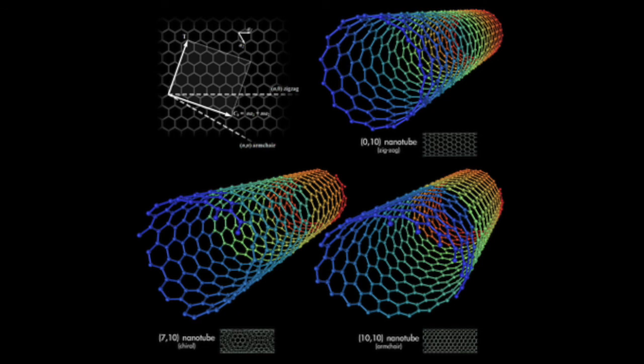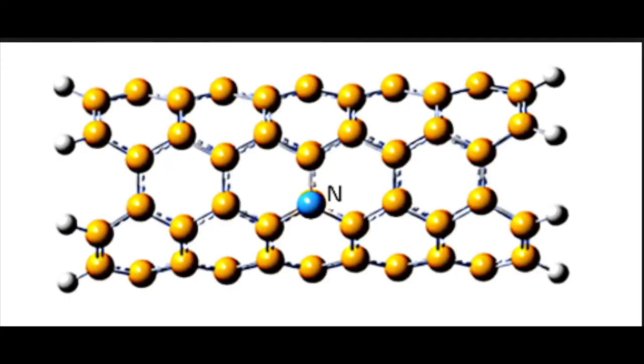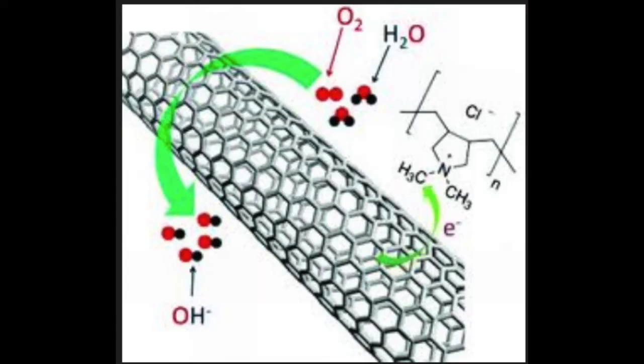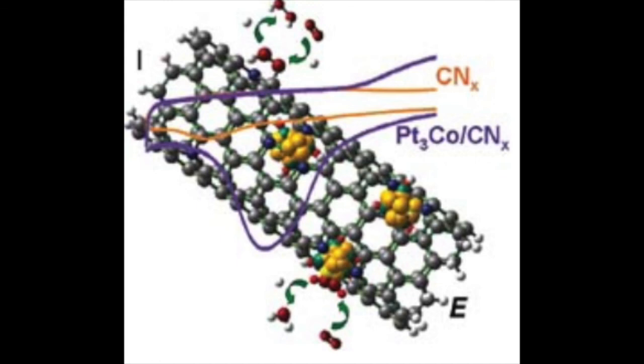There are also a few ways to dope carbon nanotubes, to make them n or p-type. First, you could add impurities by replacing the carbon with nitrogen, for example. This works similarly to how it does in silicon. Second, you can add positive or negative ions between the bundles of carbon nanotubes. And third, you can also bond atoms or compounds to the outside of the tube.